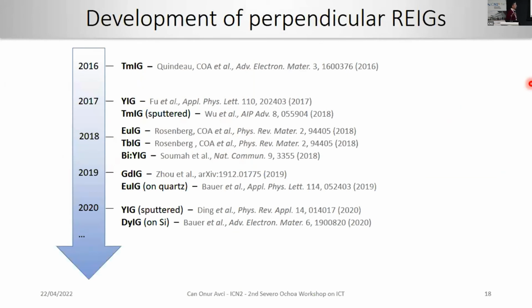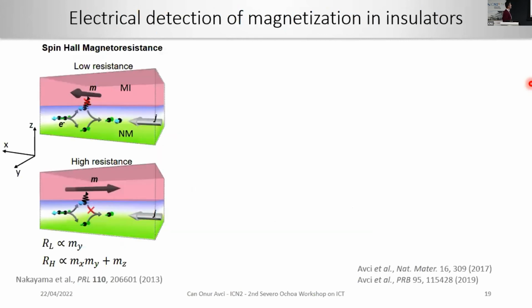My research is mainly focusing on the perpendicular magnetic anisotropy, and there has been very big progress in the last years, because perpendicular magnetic anisotropy needs to be engineered. You need to have some lattice engineering of the materials. But starting from this 2016 paper, there is a big number of materials that you can grow sub 10 nanometers with perpendicular magnetic anisotropy, and that could be very useful for most of the spintronic phenomena that I explained to you previously.